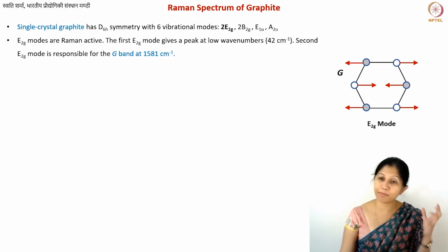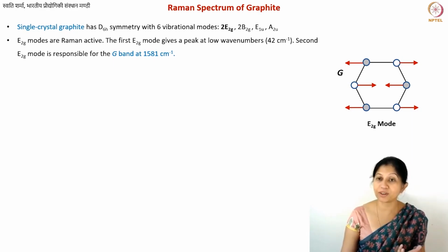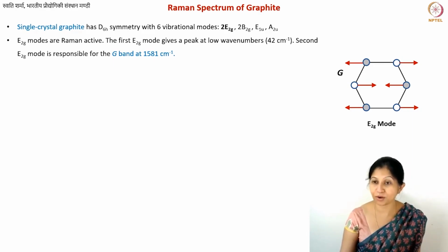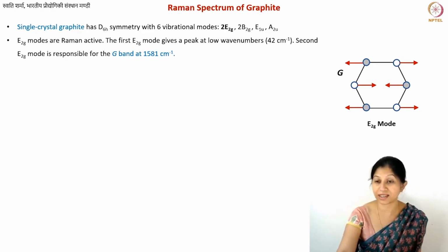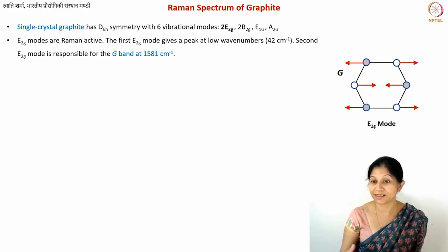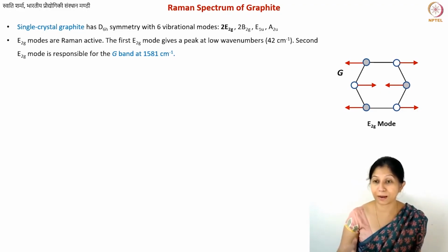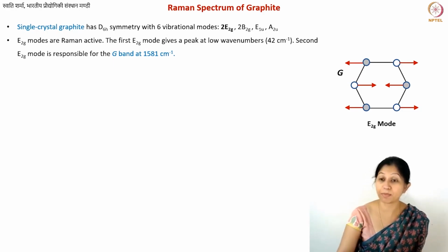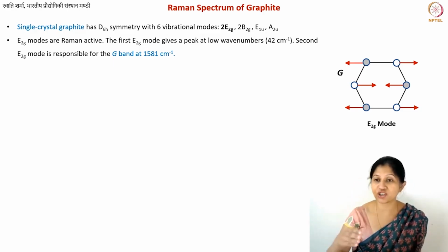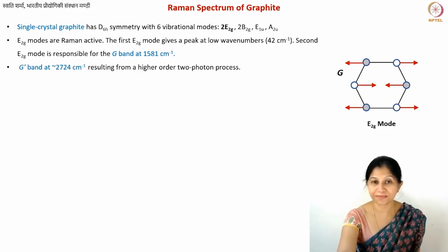So basically any sp2 site, even in a polymer, will give you this kind of vibrational mode. So you do call it graphitic, but just because you see this band, that doesn't mean you have graphite in your material. Okay, so turbostratic carbons definitely will give you some G band, but even polymers, even anything that contains these chain-like structures which have sp2 hybridized atoms, will actually give you this G band.